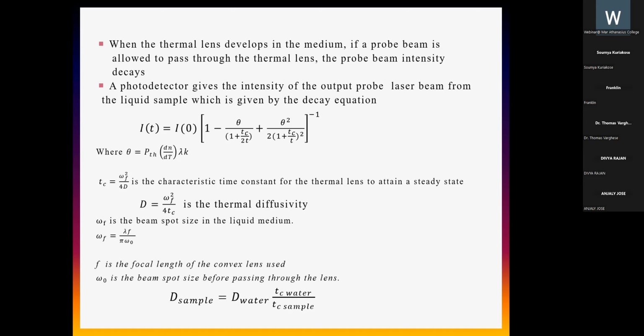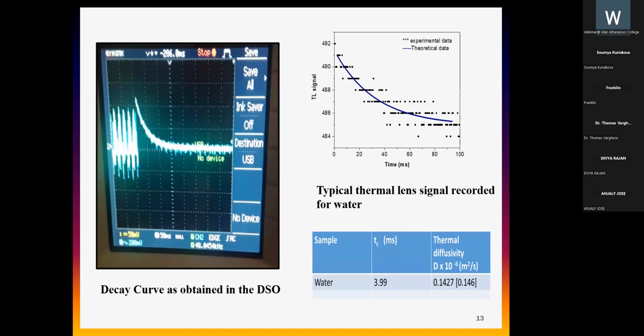Then the time response of the thermal lens can be used to determine thermal diffusivity using the equation D = ωf² / 4tc, where ωf is the beam spot size and tc is the characteristic time constant. The figure shows a typical thermal lens obtained in the DSO. We have standardized the experiment using water, whose thermal diffusivity is obtained as 0.143 × 10^-6 meters squared per second, which matches